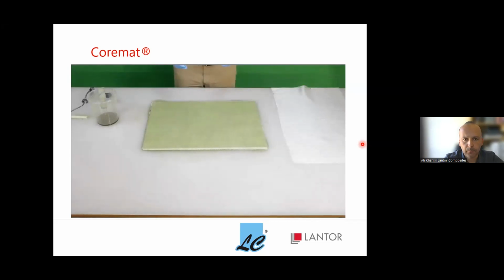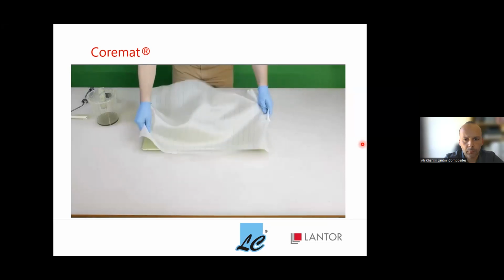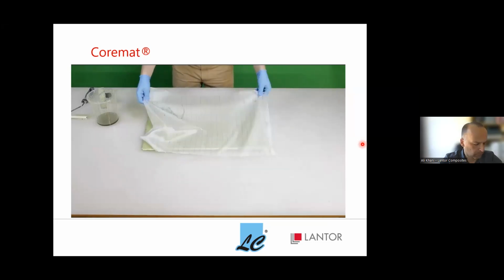When we are confident the glass layer is fully saturated, we can apply a peel ply to cover the backside. Peel ply removes excess resin after cure and creates a good surface for coating or adhesive. Although peel ply is not a structural layer, we make sure that the layer is fully saturated.